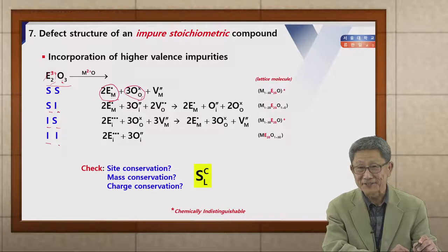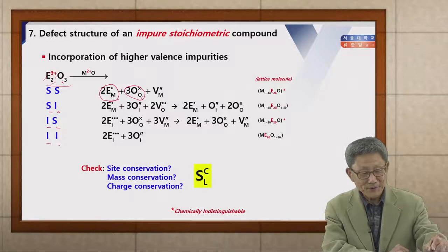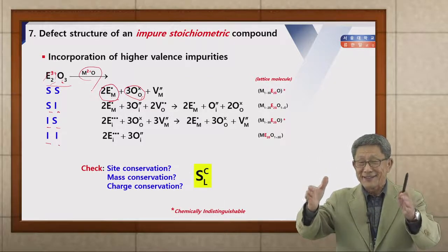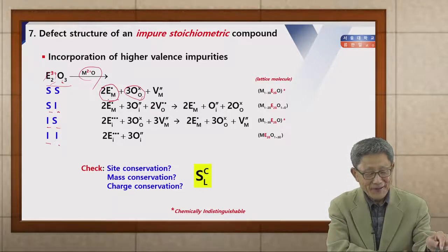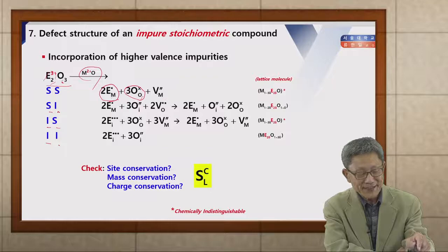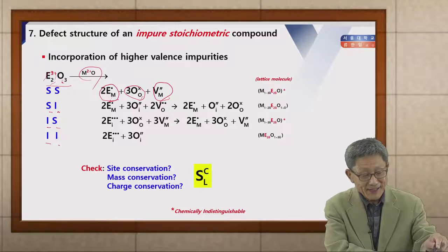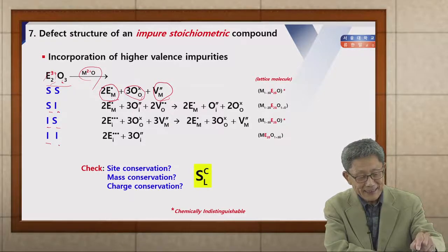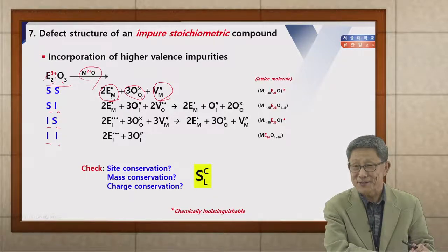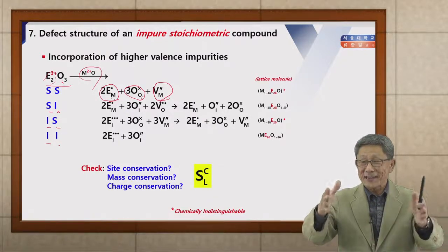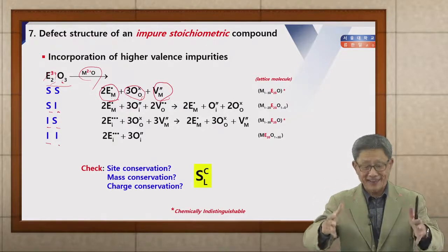What about structure condition? Okay? We used 2 cation sites and 3 anion sites. Our host lattice consists of the 1-to-1 structure. Oh, then no way, except for creating the cation vacancies. Then you see you have 3 cation sites and 3 anion sites. 3 to 3 makes 1-to-1, right? So keeping our host lattice MO intact.